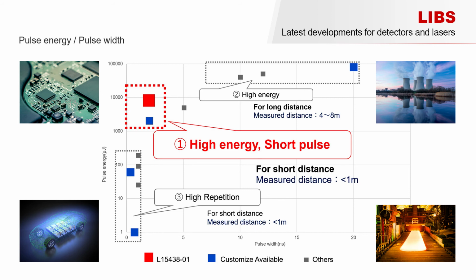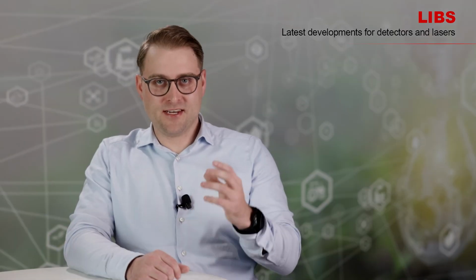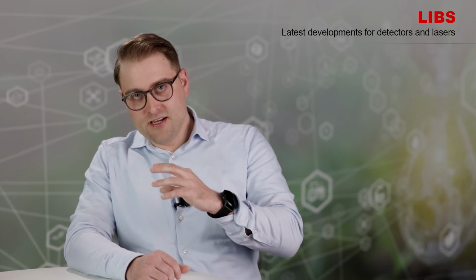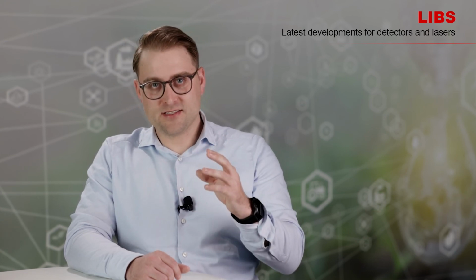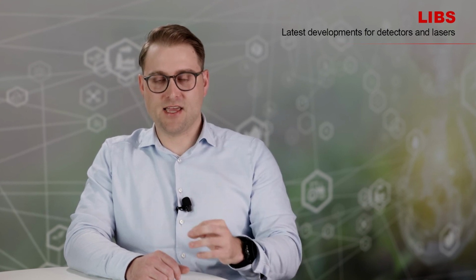This graph compares laser pulse width versus pulse energy and clearly points out that you cannot use one single laser for each LIBS application. The requirements, depending on the applications, are complex. Simply put, high energy is needed for long distances, around 4 to 8 meters, but this also influences the pulse width. For short distances, higher repetition and small pulse width are required, but the pulse energy is getting weaker. A happy medium is high energy with a short pulse. Generally, customized adjustments need to be considered case by case.